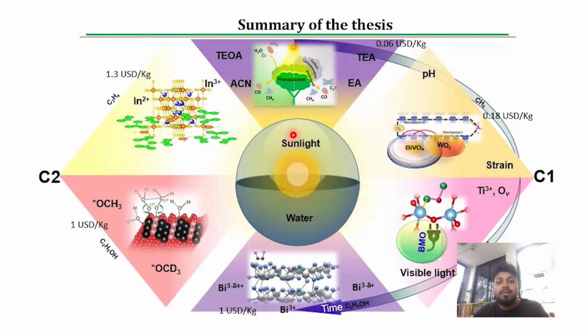In summary, we can say we have worked with different pitfalls of photocatalytic CO2 reduction when we are using TEOA, acetonitrile, TEA or ethyl acetate as organic additives. We have played with the pH and strain in the next chapter, and we have made a heterostructure like this. With that, we got methane as a product. Then we again worked with a heterostructure model with bismuth molybdenum oxide and titanium dioxide, and we got methanol over here. Upon charge polarization technique, we got ethanol, and then ethanol was again improved in case of composite catalyst where red phosphorus and bismuth molybdenum oxide was used.